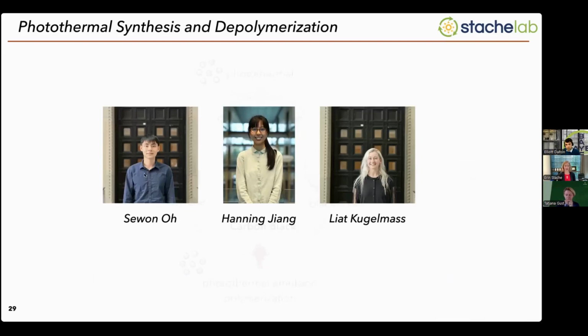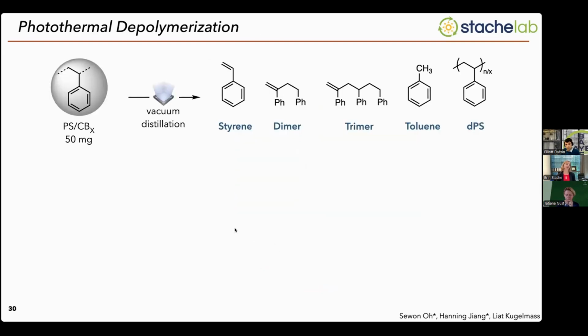So all of this work was carried out by Sewon and Hanning, and Liat started all of this work. And so the first thing we did is we made pure, pristine polystyrene carbon black composites. So we took styrene monomer, we took carbon black, we polymerized them together and made a carbon black solid composite. Then we exposed this to visible light irradiation, and particularly using vacuum distillation to recover the styrene monomer.